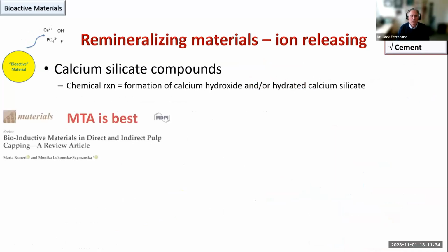We have other calcium silicate compounds as well, but if we look at some of the literature with respect to these, we typically relied on calcium hydroxide. Calcium hydroxide, I would say, was the first bioactive material produced, in the 1920s. And MTA has pretty much come along and supplanted it. And we see that for a variety of different reasons.